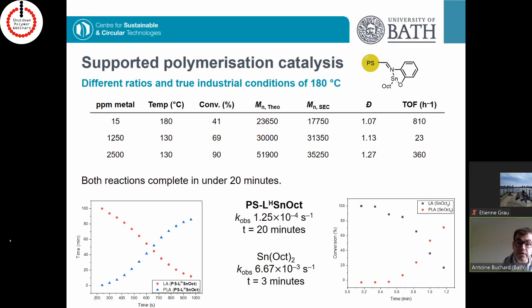What we've tried to do is really to use it under industrial conditions, looking at the effect of the temperature, and in that case, still monitoring the reaction by IR. What you can see is at 180 degrees, which is the type of temperature that people use in the industry, yes, for tin octanoate, the reaction is still faster, and the reaction proceeds in 3 minutes.